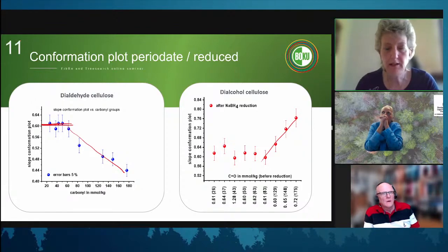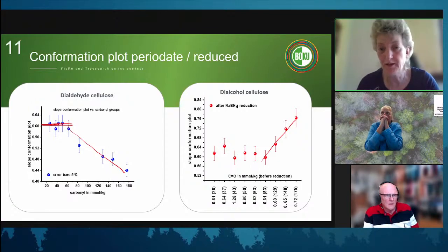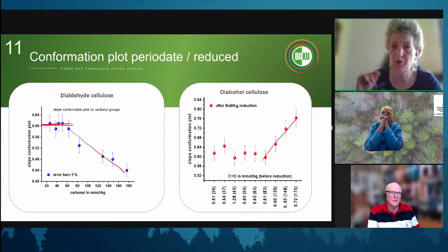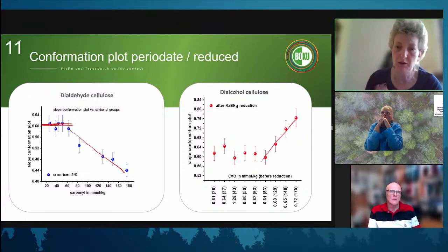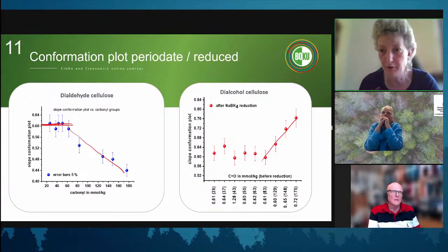We have not done any static light scattering on that. We can also assume that dN by dC will change. Yes. We did not really. I mean, it's very hard to measure for cellulose. And it would mean basically that you're able to address the concentration very accurately when dissolving, which is already difficult for cellulose.